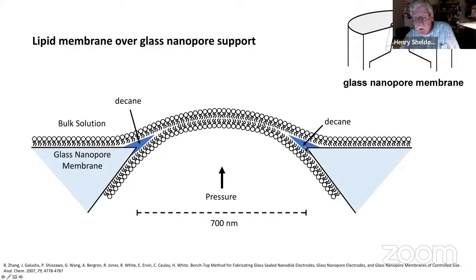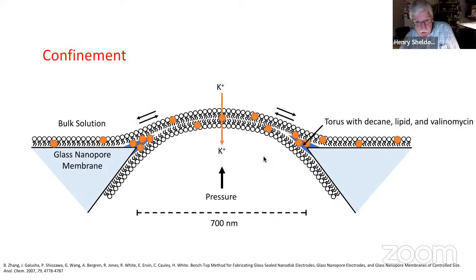So there's a little torus region around the circumference of the nanopore that contains decane, and it contains excess lipid as well. And the confinement part of this is that the orifice of this nanopore is so small that you would expect, when you put the valinomycin in the bilayer, you're only going to get a few molecules in the active region where the potassium is being transported, all right? And so I've drawn it here with 5 or 6 molecules. I think typically we see 20 to 100 molecules in the bilayer above the opening here. But what we're doing here by making this nanopore really small, we're reducing the number of molecules that we're going to make the measurements on.